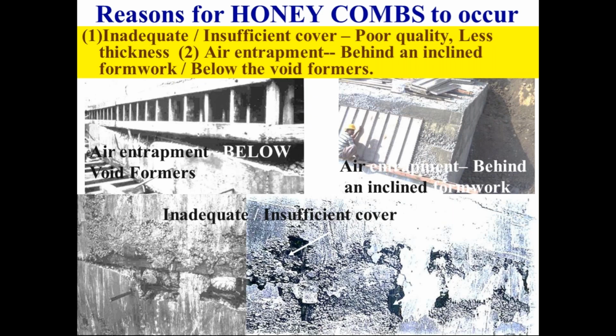Many a times, there are void formers used in concrete structural members, but if there is no escape for the air, you see, when we compact and vibrate the concrete, the air trapped gets dissipated, and many a times if there is no escape, it goes and sits below the void former, like you see on the beam on the left hand side top slide.